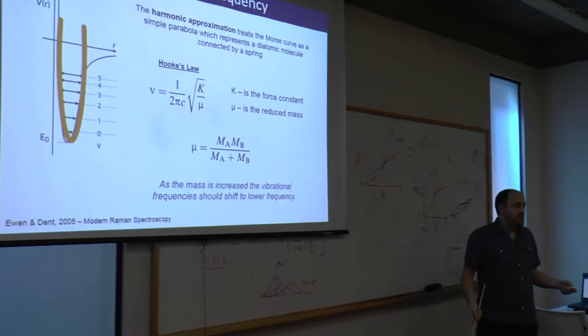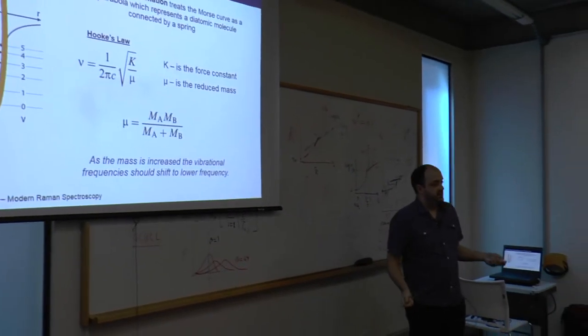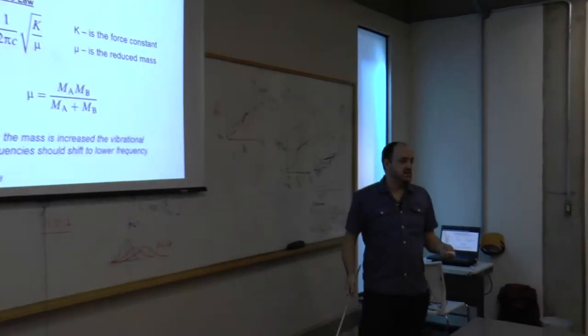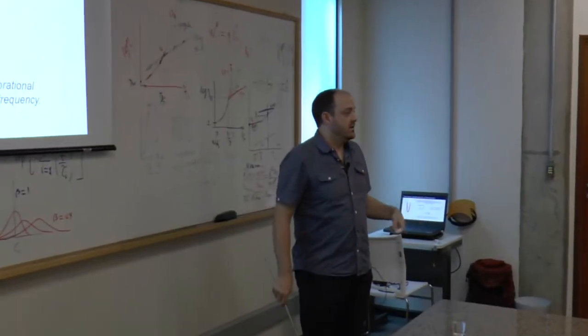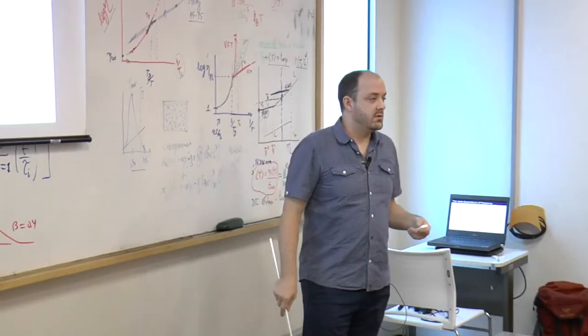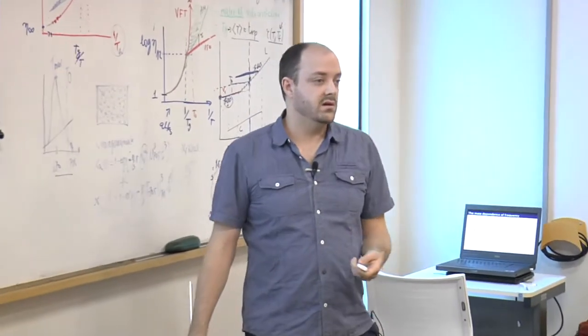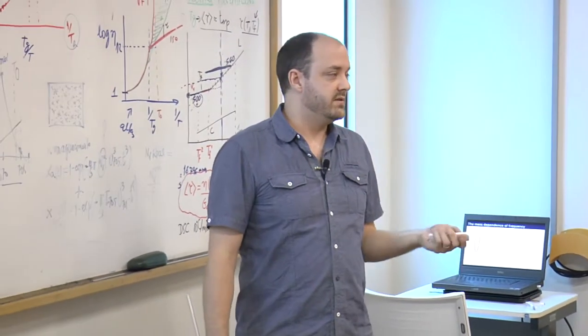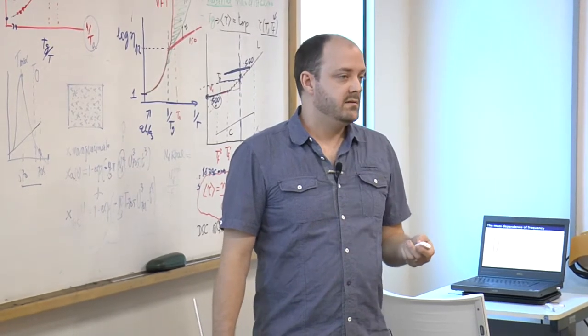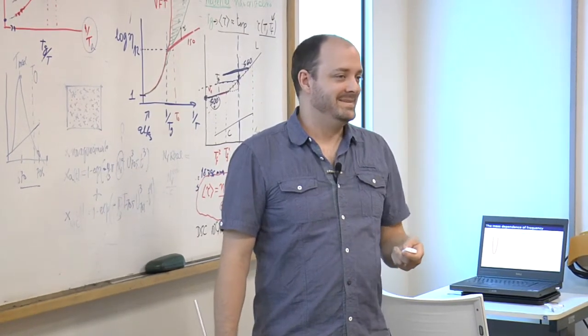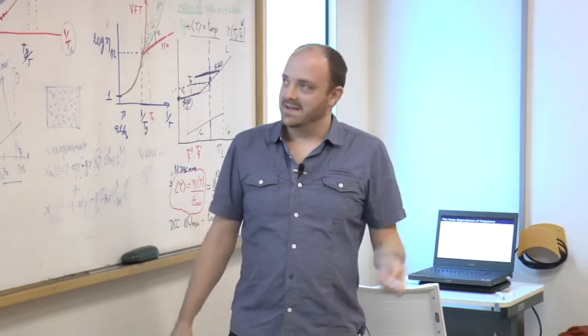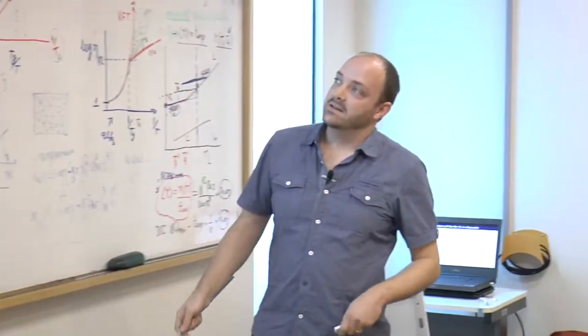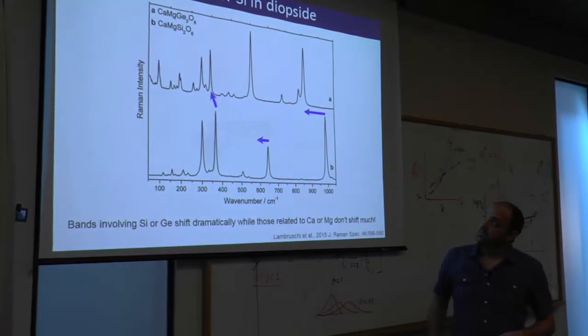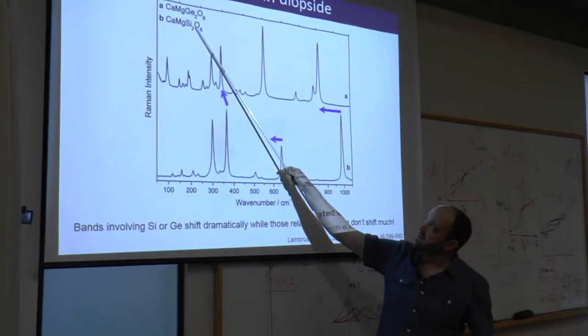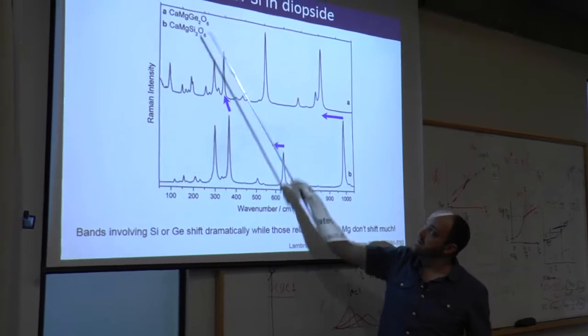So what's your prediction about the frequency if we increase the mass of the atom we're looking at? Take, for example, a substance where we substitute germanium for silicon. What do you expect for the shift in the peaks? Yeah, exactly. Perfect. So here are two spectra of a diopside and a germanium diopside, calcium magnesium silicate and calcium magnesium germanate.